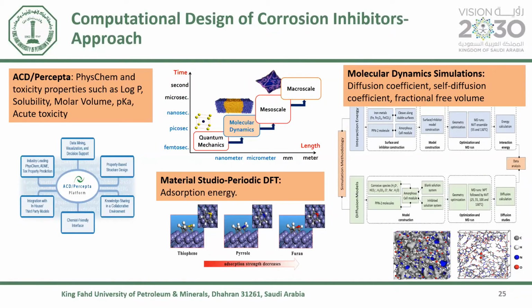So this can give you a lot of diffusion coefficient constants that you can then use. If you are screening like 50 molecules, it could help you to reduce the time of testing a lot of molecules by just trial and error. So we combine all these properties, and then it helps us to really screen a lot of molecules in different environments. Even if you want to use polymers, you can also look at permeability, the diffusion of these small molecules in polymers. So this has a lot of applications, even for non-metallics. You could use simulation like this to study permeation of molecules in polymers. So this is very important too.